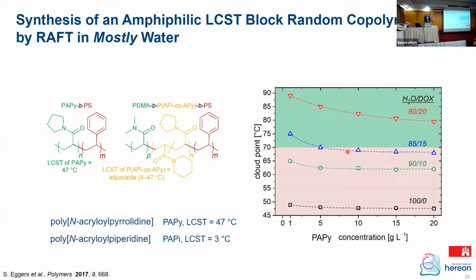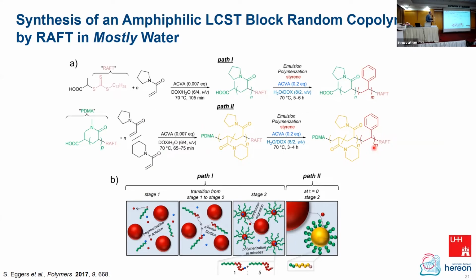And here what you see are cloud points of this PAPy, with a cloud point around 47 degrees in pure water. When you add dioxane, this LCST is increasing. And here in the green area, a temperature range above 70 degrees, we are now in the dissolved state. That means in that water-dioxane mixture, we can polymerize this monomer and get a homopolymer in solution. And then we can add styrene, and depending on what we do exactly, we end up with styrene emulsion polymerization, because in this dioxane-water mixture, styrene is not really soluble and it forms droplets. These are these big red balls, which you see here.